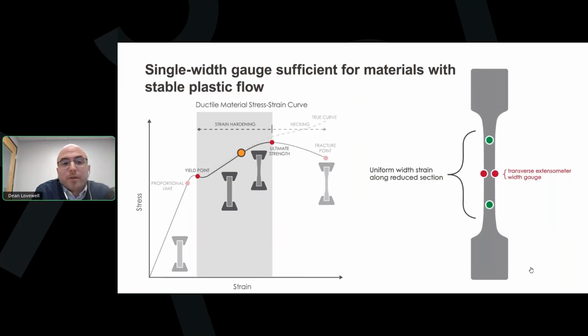Now, for materials with stable plastic flow, this method of a single width transverse extensometer is sufficient, since for the domain of the strain hardening region, which we see in this graphic, the width strain is homogeneous. You can see that the area between the green gauge marks reduces uniformly, and so the red dots are sufficient to provide the representative strained width.